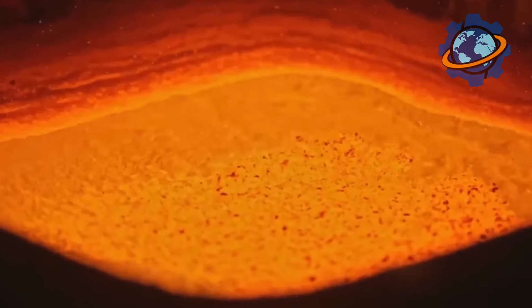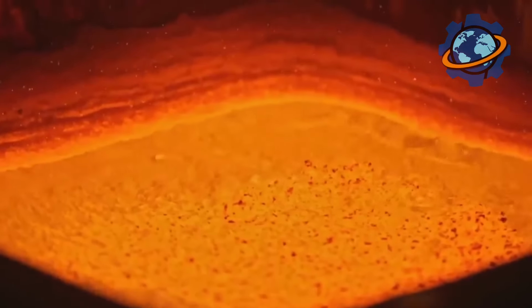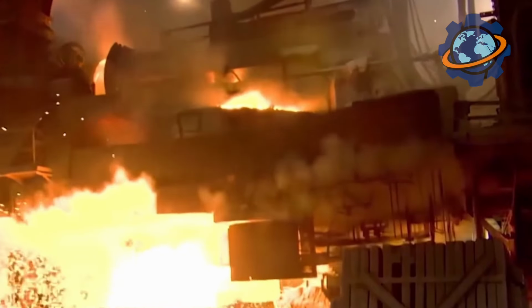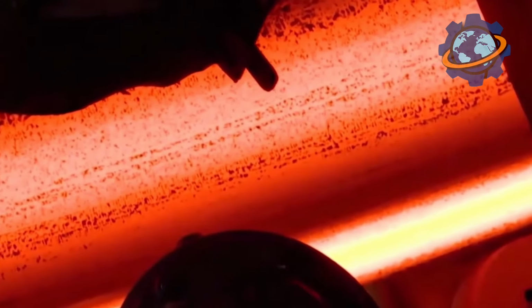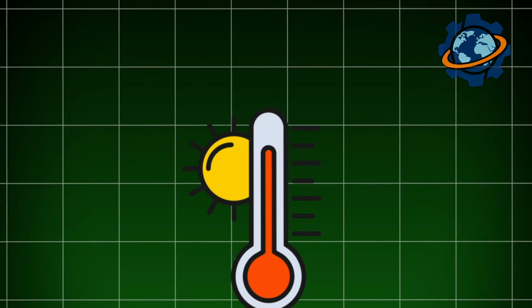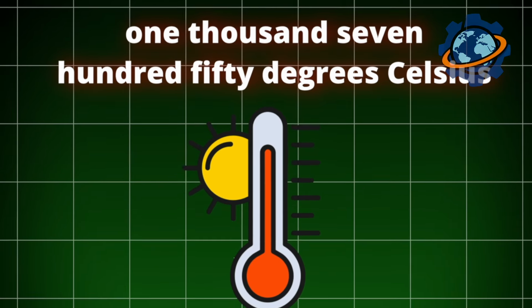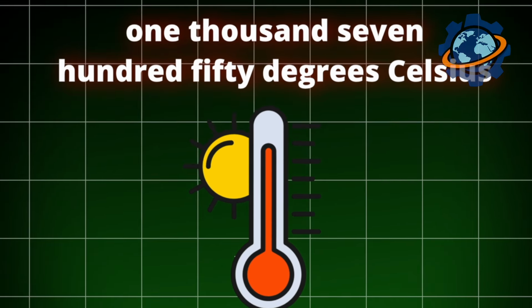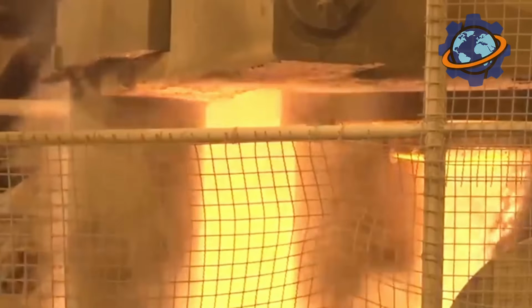The brick enters the fiery tunnel of the kiln, where a true rebirth awaits it. Slowly moving through different zones of the kiln, it is gradually heated to peak temperatures, which for chamotte brick are 1,400 degrees Celsius, and for high alumina types can exceed 1,750 degrees Celsius. This is not just drying, it is a deep metamorphosis.